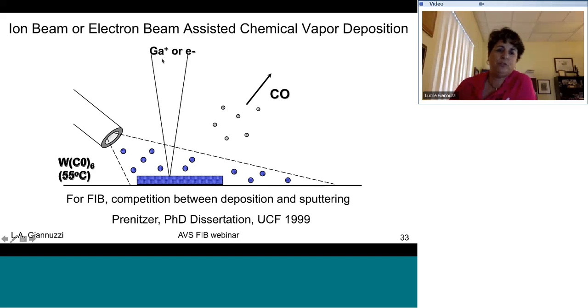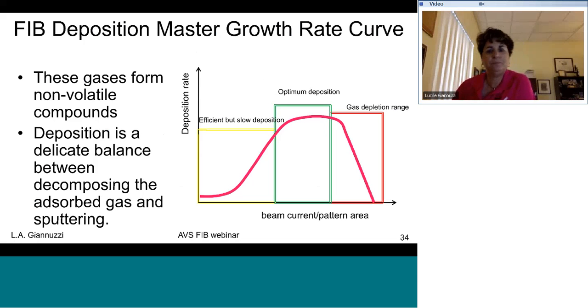Okay, so where you deposit or where you scan either your gallium or your electron beam, you're going to crack the gas, resulting in a deposition. And remember, for heavy ions, you've always got the competition between deposition and sputtering. So you're going to have this master growth rate curve, and for deposition, the curve looks something like this. You're going to have your deposition rate versus your ion beam current or pattern area. So as you use a very small beam current, the deposition will be very efficient, but it's going to be very slow. So as you turn up the beam current, the deposition rate is going to increase. And there's going to be a sweet spot here. This is your optimum deposition rate, optimum beam current, and then you reach the so-called gas depletion range.